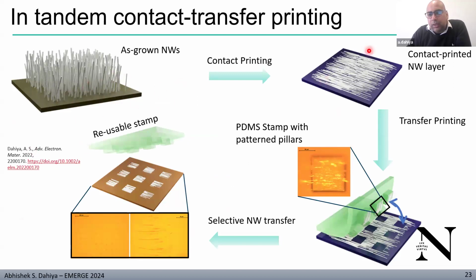So we have this nanowire grown, then we do contact printing to have it uniformly all over the area, and then we bring the stamp. As you can see, these are the pillars on the stamp where we are picking the wires, and not on the area around them, and then you can make this kind of array of nanowires printed.